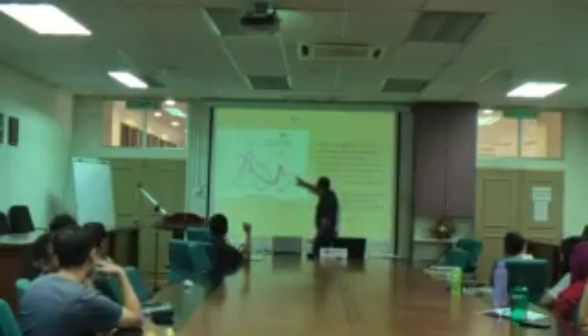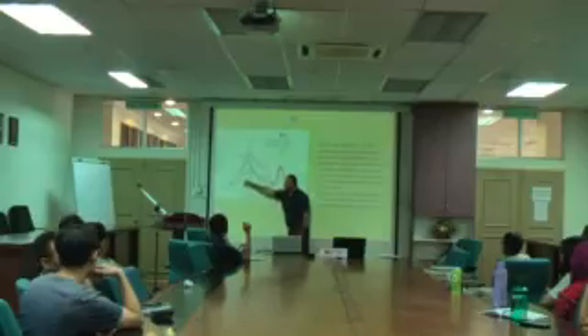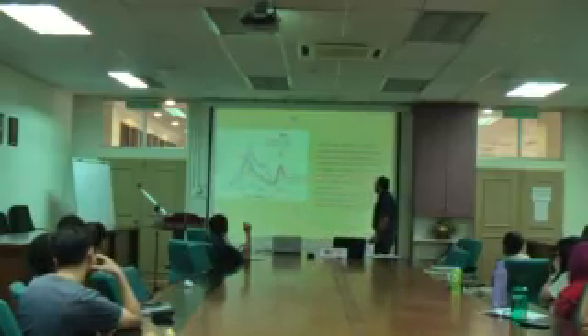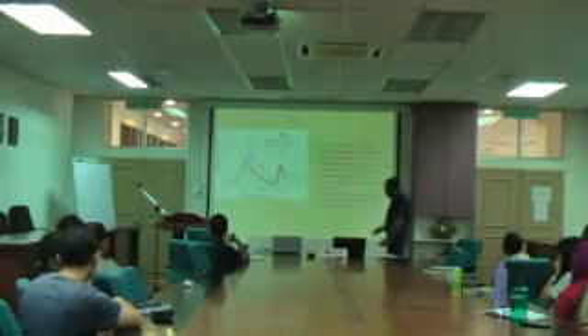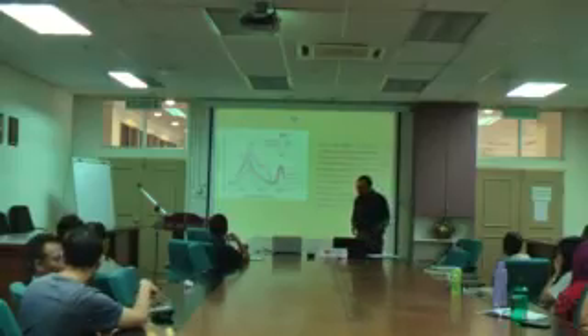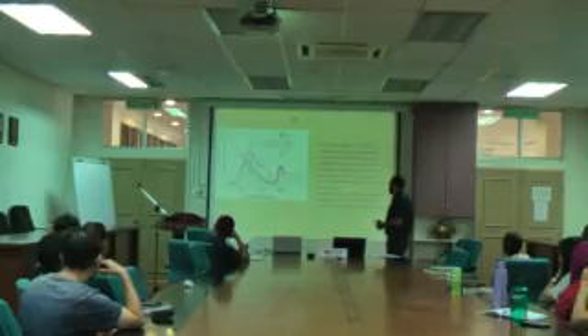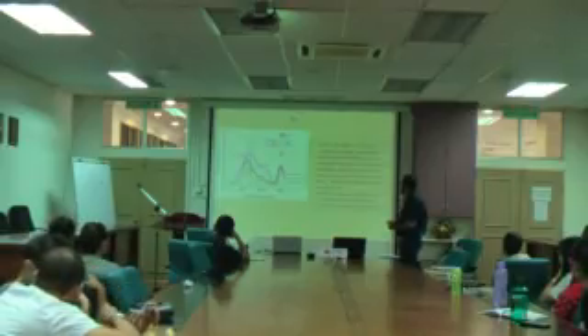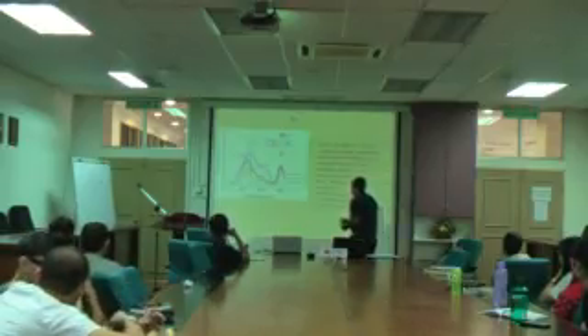So by increasing annealing, we can see this peak decreases. The intensity decreases. It's because of the number of electron hole pairs which are responsible for emission. But these peaks remain the same by increasing the annealing.